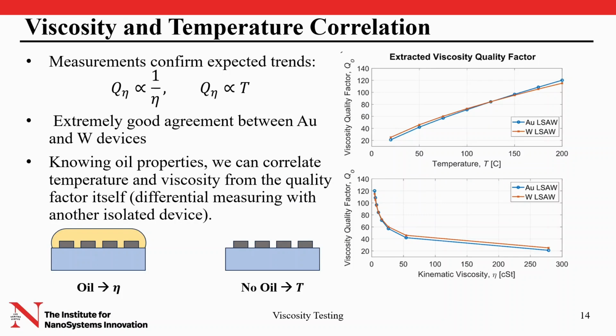As we can see in the plots, we have an almost perfect linear trend for the viscous quality factor and the temperature, and an almost perfect inverse linearity for the viscous quality factor and the kinematic viscosity. But what is most interesting is the perfect agreement between the tungsten and gold resonators, which led us to conclude that these measurements were accurate and validated each other. Of course, in a real case scenario, having such high temperature coefficients of frequency, as I said, minus 65 ppm/Kelvin, we would need to perform a differential measurement in which one resonator is exposed to the oil while the other is isolated from the oil, and we can track the temperature shift on the first one while the viscosity can be tracked with the resonator exposed to the oil.